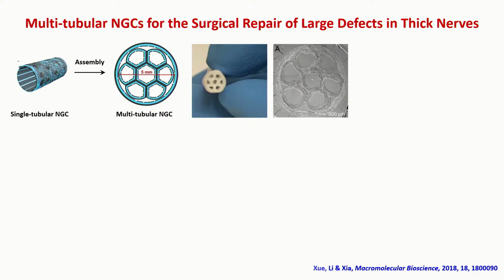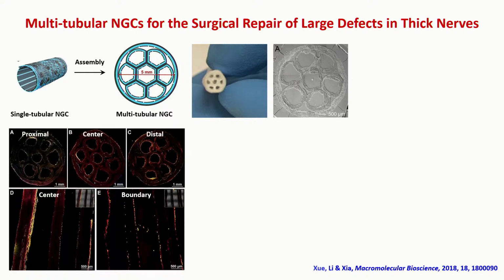Basically, we take multiple single tubular nerve guidance conduits and assemble them into an array. We make these multi-tubular structures. And what's the advantage? Here we can easily target thick nerves. Depending on the diameter of the nerve, you can increase the number of these single tubular conduits, so you can really have a good match. We can also differentiate bone marrow stem cells inside these multi-tubular scaffolds. We have demonstrated that there's no difference compared to the single tubular ones.